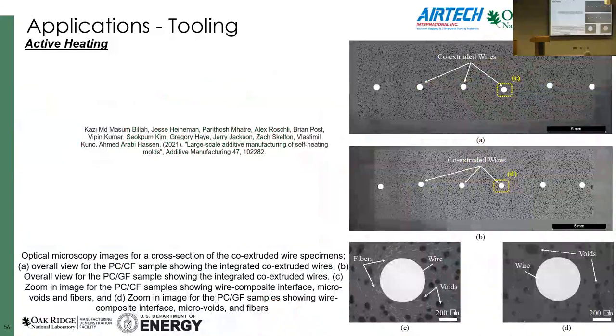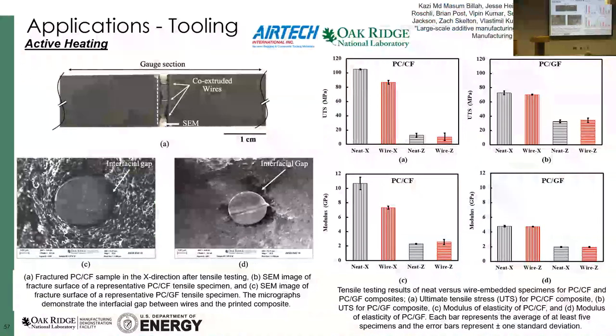We did our typical material science just to see the distribution. Are we depositing it where it needs to be? As you can see, all of these are wires. And as you can see, we did mechanical testing to see if these wires are giving us a hit on the properties or not, which we found that yes, it is dropping our modulus and a little bit on the UTS. But why? Because actually we literally got an off-the-shelf nichrome wire, and we put it in one of our materials. We didn't condition the wires.